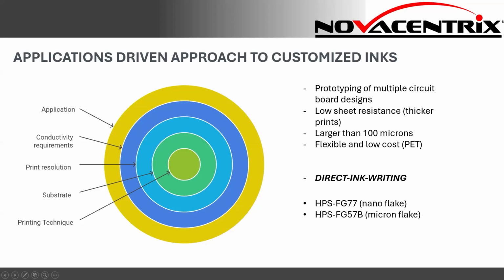So with that in mind, we have worked with Voltera for a long time, and a couple of the inks that we worked with them on back in the day were the HPS FG77. The HPS there stands for High Performance Silver. There were two different versions, the FG77 and the FG57B, and I'll go into more detail on each of these two inks. The FG77 is a nanoflake based ink, so the particle sizes are much smaller, and FG57B is a micron sized flake ink. All of that to say, after working for some time with Voltera, we realized that certain improvements were needed, and that's what gave rise to our HPS U11 ink.